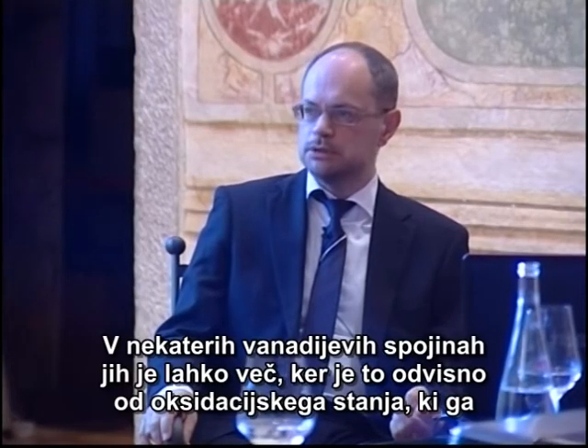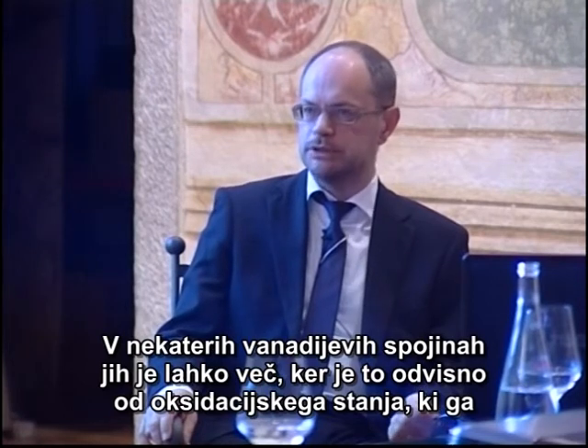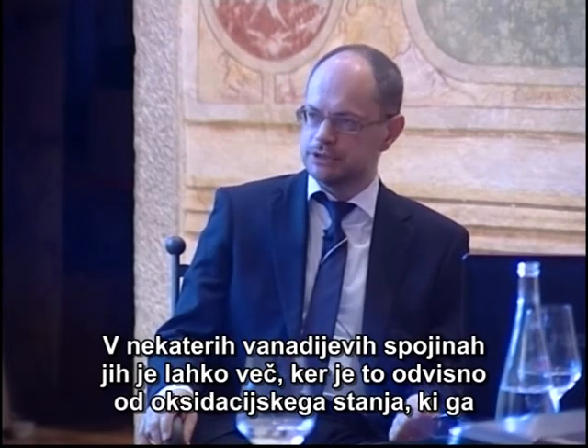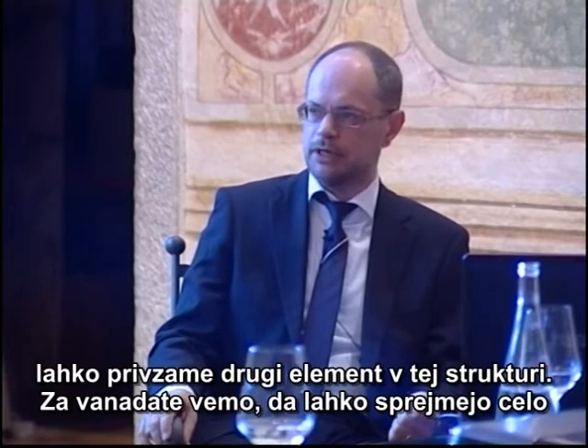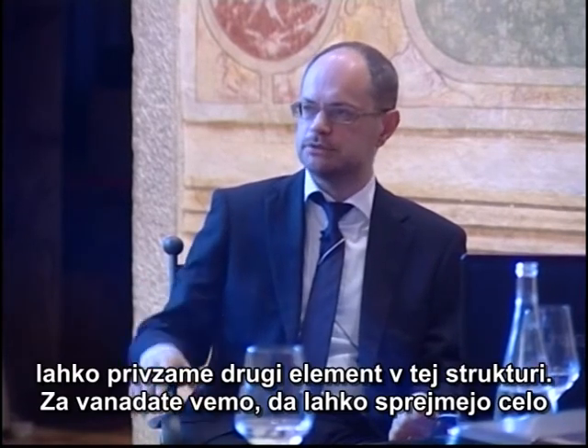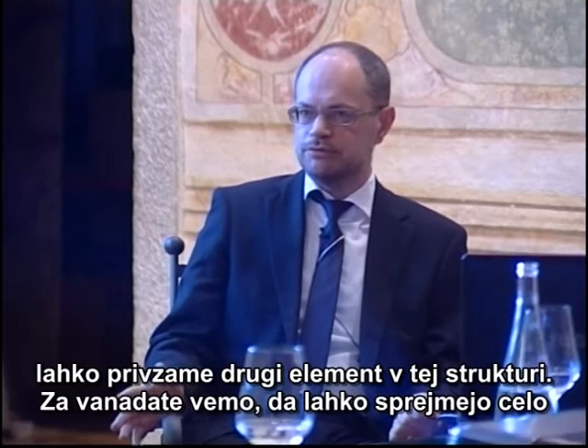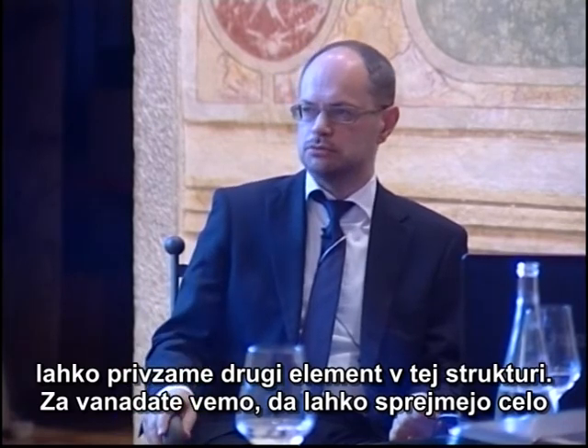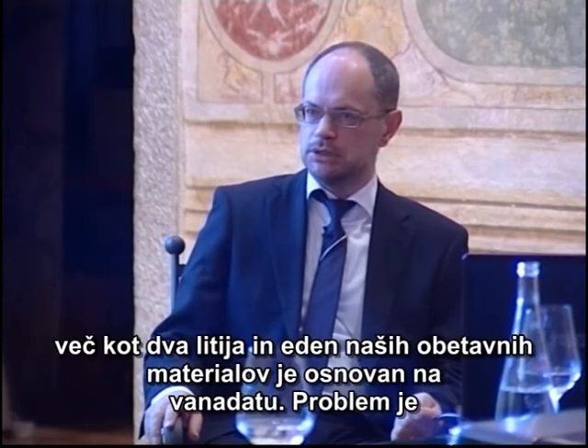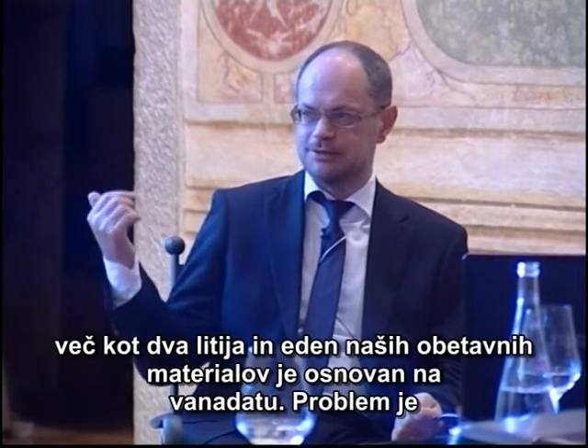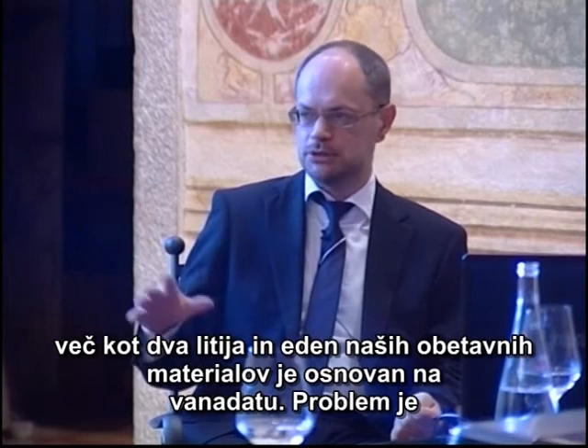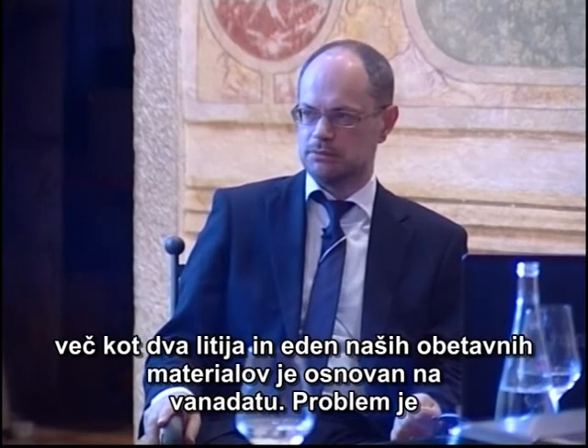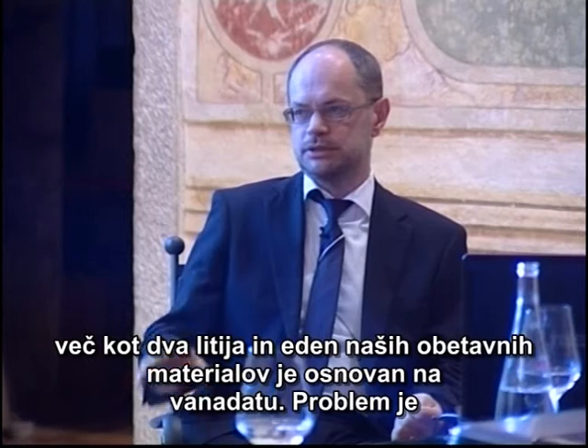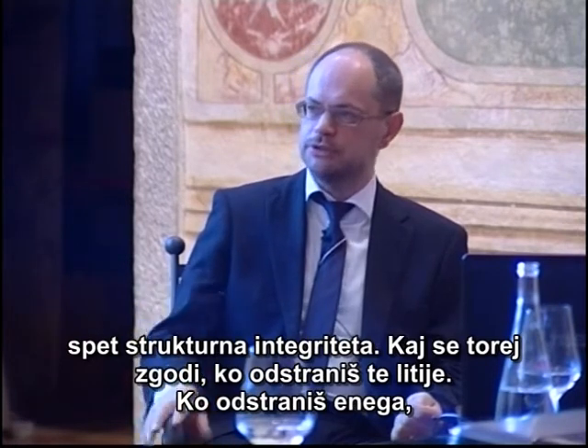In some vanadium compounds, there can be more, because it depends on the oxidation state, which can be adopted by the other elements in this structure. And vanadates are known to exchange even more than 2 lithiums. And one of our promising materials is also a vanadate-based material. Of course, the problem is, again, the structural integrity.